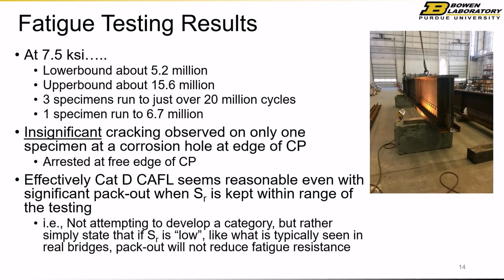So here's the 30,000 foot results. I'm not going to get into the details and show you each specimen. Now, bridges operate at low stresses, right? In reality, we talk about the categories. Our goal, fatigue categories, our goal was not to define a fatigue category, right? So we're not running at 20 KSI and these high stress ranges that we typically do. Because in real bridges, when you instrument them, you operate around 3. Maybe you'll get a 5 KSI once in a while. Our goal was to try to say, in real operational circumstances, does the pack out hurt you, right? Because that's what you're dealing with, bridges in real service.